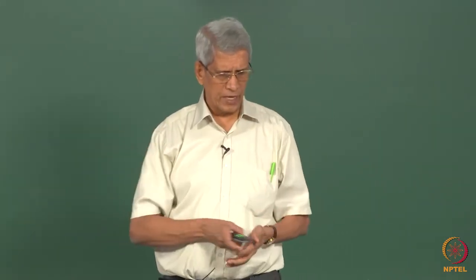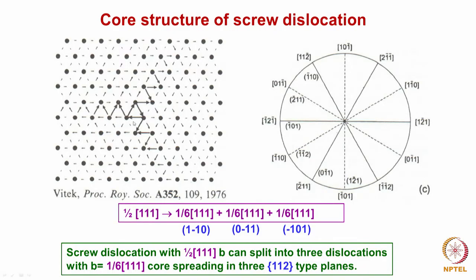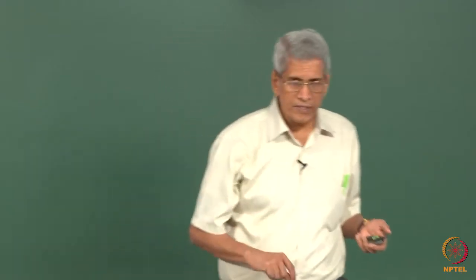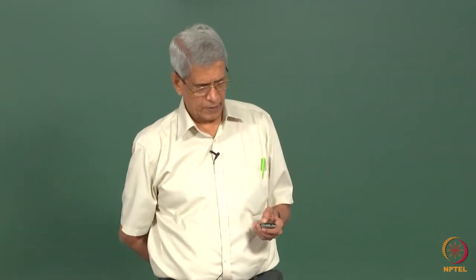Similarly, if we look very carefully, we can notice that even in these directions also, we can see some asymmetry of the displacements, which could be seen even on 112 planes also. There is some component of the split, especially 1/6 111, part of it is in 110 type of a plane, part of it is in 112 type of plane. But what is essentially interesting is that if we try to deform this material,